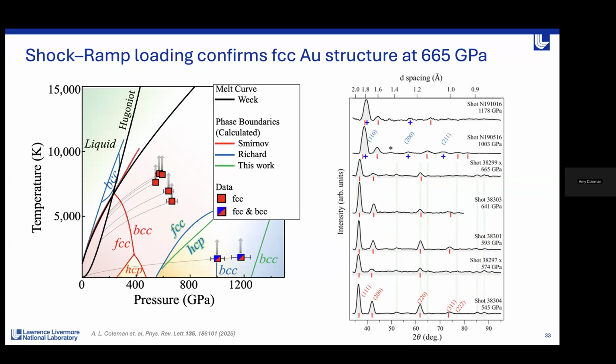Actually, when we collected this data, it prompted us to go back and look at the data from the original paper. There's a lot of overlap between the authors of that original paper and this recent PRL. So we took it upon ourselves to revisit the data, and with improvements in analysis techniques and background subtraction, we found the original data set was actually consistent with FCC.